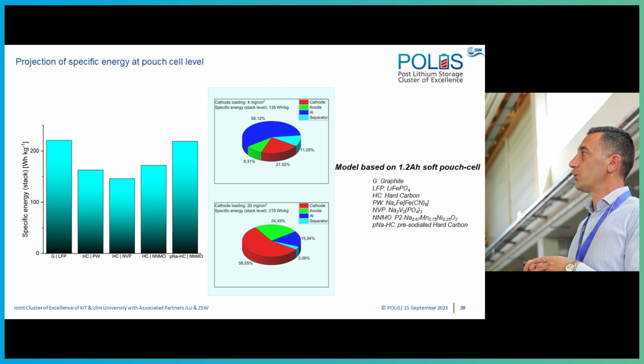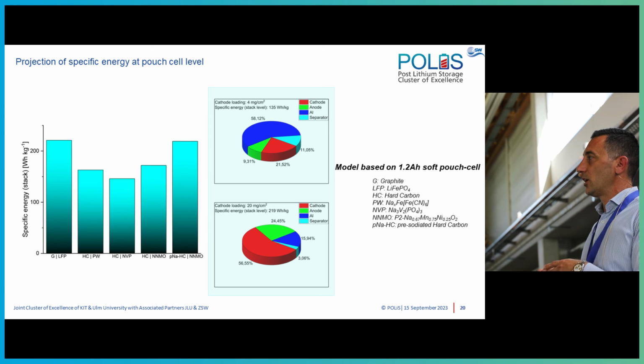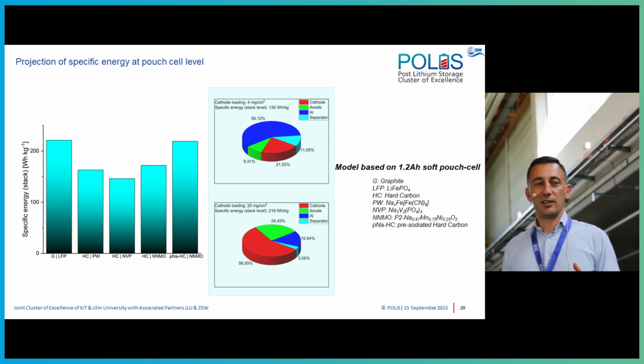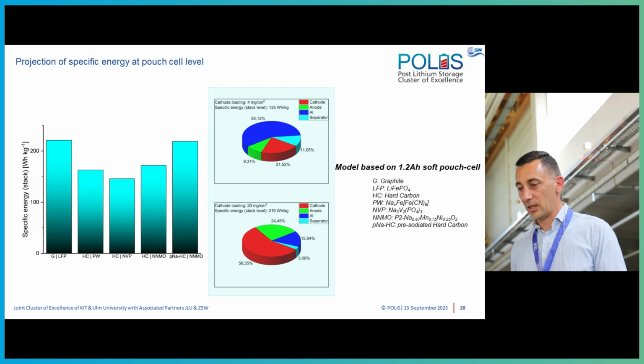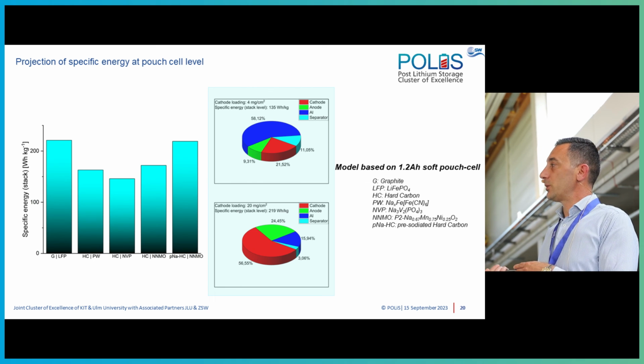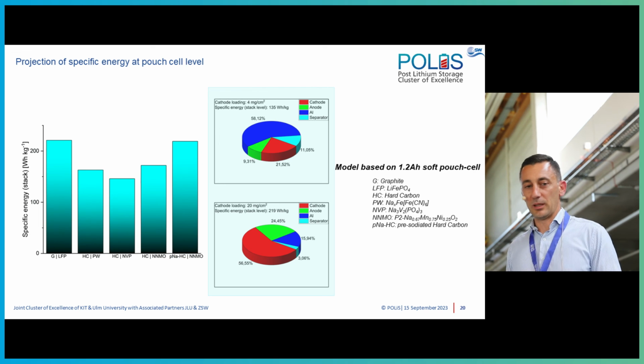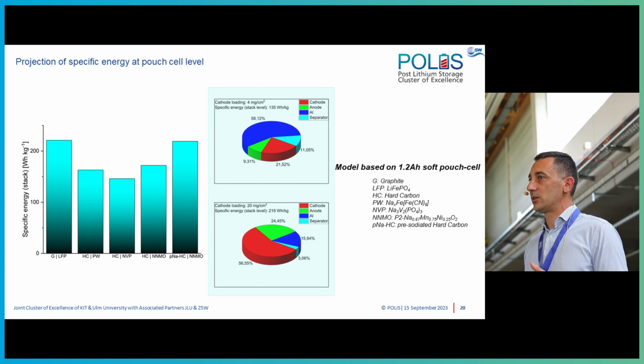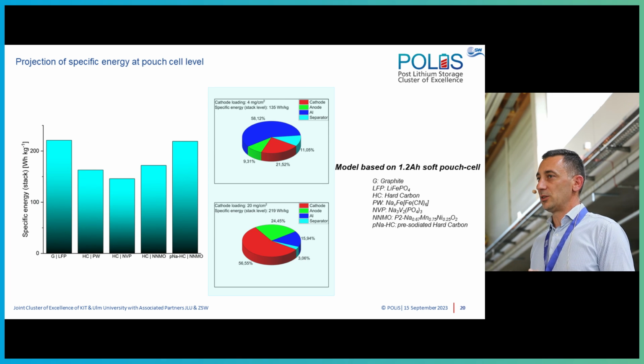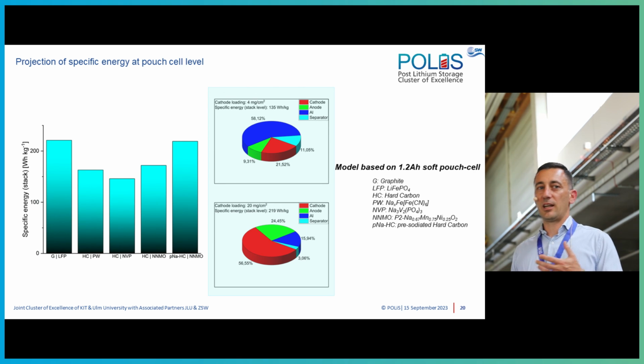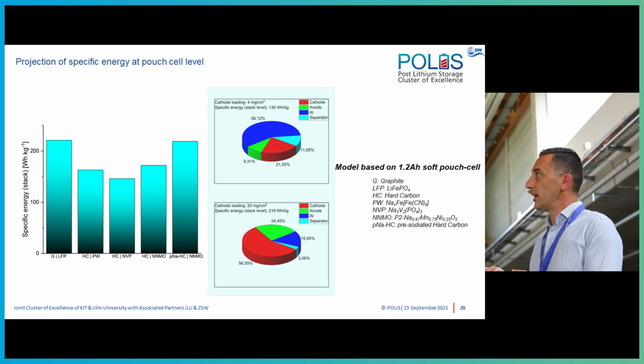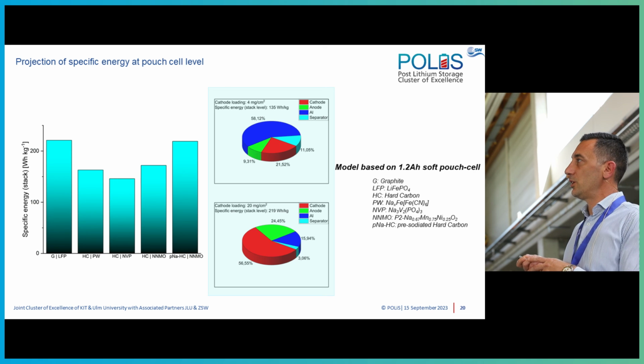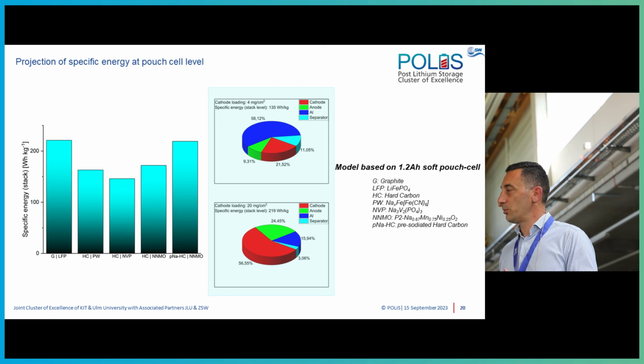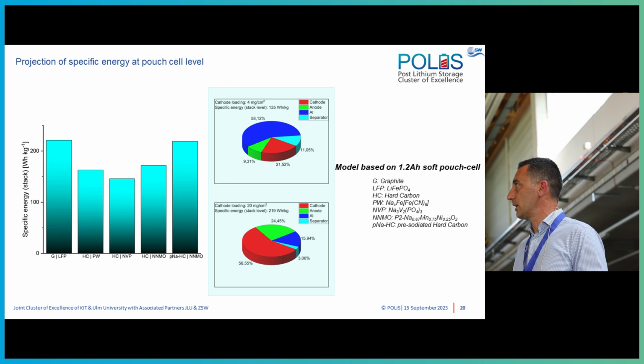So what we have to do to reach the specific energy performance of an LFP graphite cell is to pre-sodiate the hard carbon, and I'm glad that there are activities in that respect within Polis. I have to mention also that in this case, I took some data from literature, and for the first cycle Coulombic efficiency, I considered about 75% for the hard carbon, whereas for graphite, I considered over 90%. So if we can get to the same level, then this gap will reduce remarkably. I'm not saying we will be on par, but probably a few percent less.